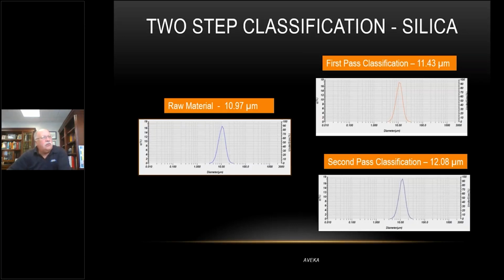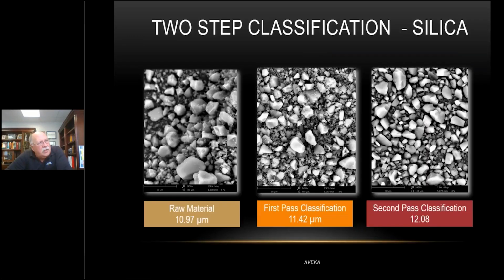And so we did this first classification. We went from 10 almost 11 microns up to 11.5 microns, just by cutting a very small shoulder off the small end of this system. As it turned out, we didn't get the result that we wanted. There was still an incredible amount of fines that were in there. So we did a second pass with the second little nibble on the system. And the results that you can't see here with the particle size distribution, I want to show you on this next slide. So here's our raw material, our silica raw material.